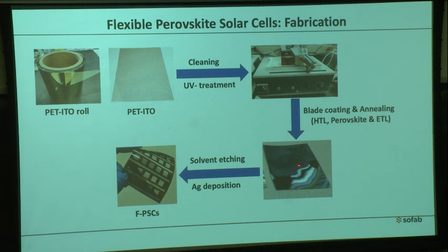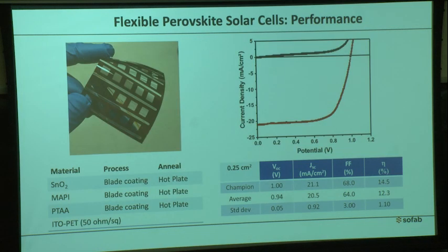We deposit tin oxide directly on top of the perovskite, and after metal deposition, we made a flexible perovskite solar cell. After that, we measured power conversion efficiency, and we were able to get power conversion efficiency up to 14.5% on the plastic-based substrate. That was very good.